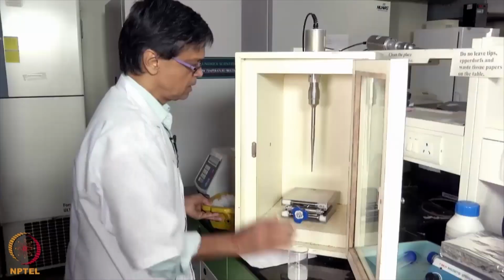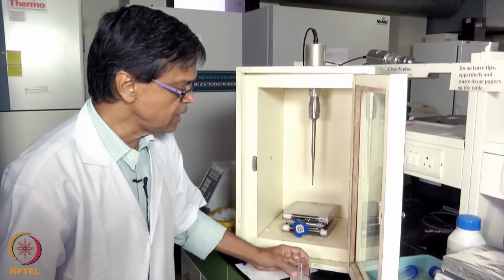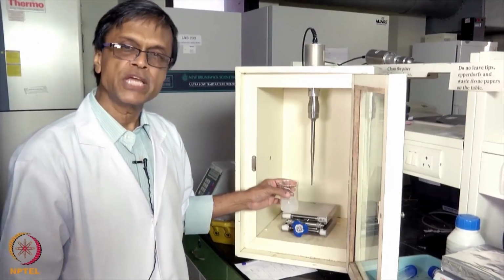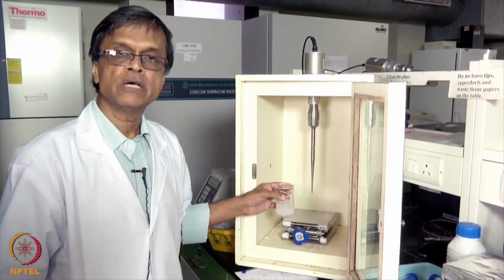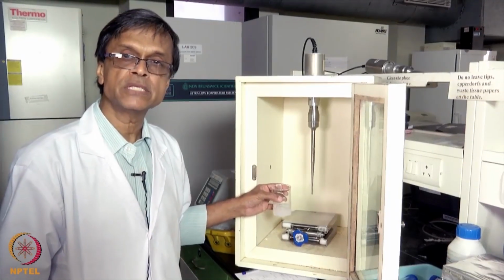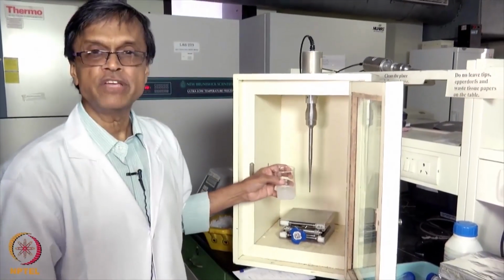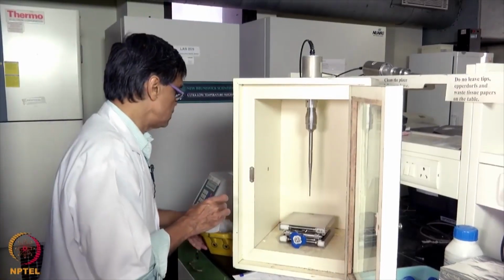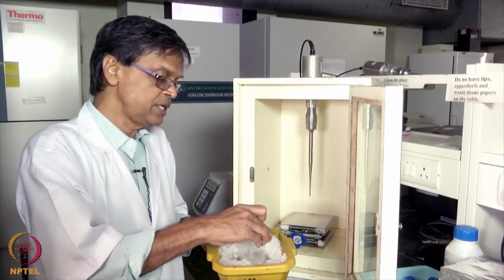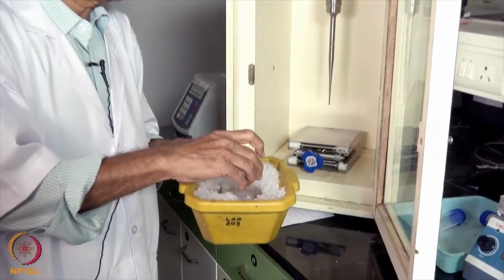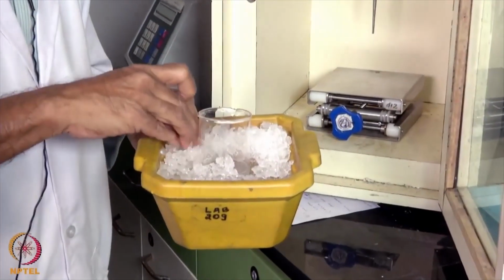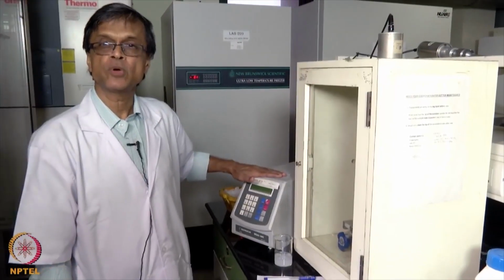We need to use the probe sonicator to arrive at nanoparticles of beta glucan, okay, stabilized by polyvinyl alcohol. This is the probe sonicator, and we have to keep our sample inside. The sonication will be done for 5 minutes. The sonication will be on for 9 seconds and 1 second off. Because a lot of heat is produced, we have to keep the whole sample inside the ice bath. As you can see here, this is the control unit for the probe sonicator.